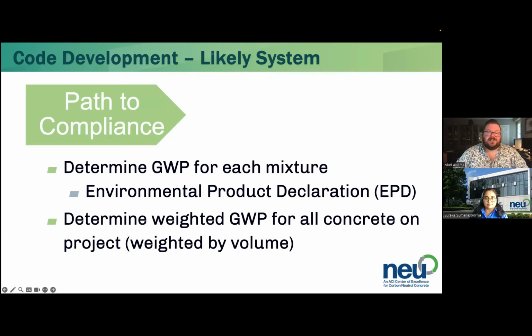The path to compliance for this is to determine the global warming potential for each mixture. The easiest way to do that is by getting environmental product declarations created for each of your concrete mixtures. And so moving forward, we're hoping that more and more concrete companies start to avail themselves of developing EPDs so that they can truly know what the global warming potential, the embodied carbon of their concrete mixtures is. And then once you have that for each mixture, you can essentially create a weighted global warming potential for all of the concrete in your project, right? So even though you might have some concrete with a high global warming potential because you need high early strength for removing formwork for one area of the project, you might also have some concrete for a sidewalk that has a relatively low global warming potential. And so by weighting those together, you can get an average GWP for the whole project that will meet your limits.